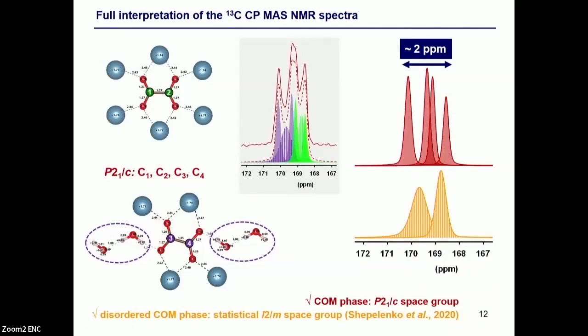So, all in all, we now have a full interpretation of the carbon NMR spectra for the monohydrate. First of all, there is a structure characterized by 4 peaks, which are really sharp. Look at the range of the chemical shifts: the whole story lies within 2 ppm. And it corresponds to the standard structure, which has been reported in the literature for decades, with the space group P2(1)/c, with 4 inequivalent sites.